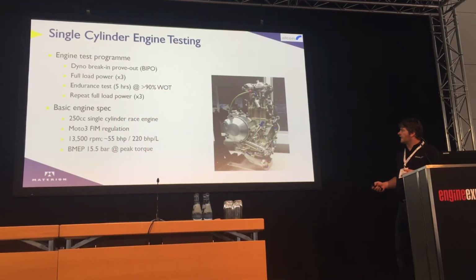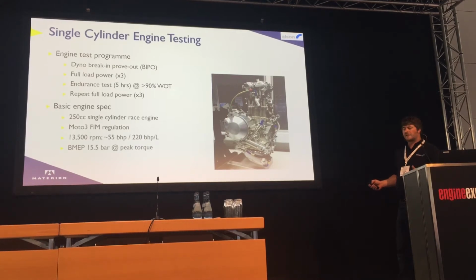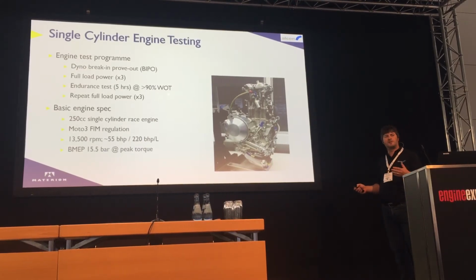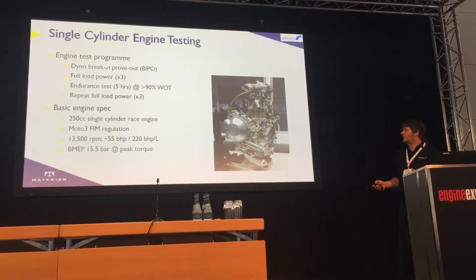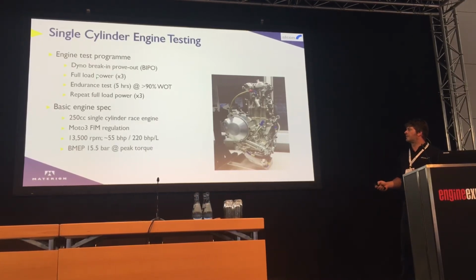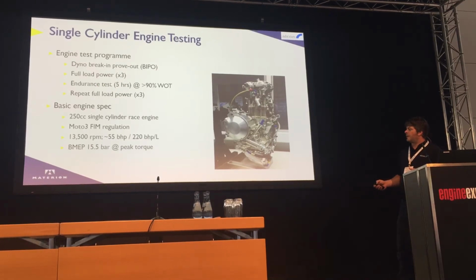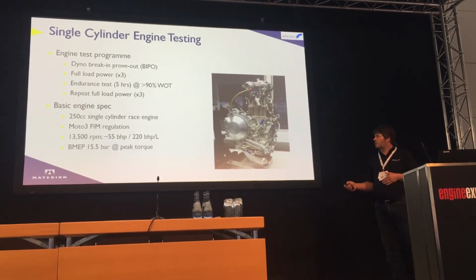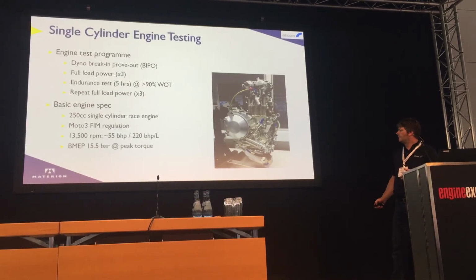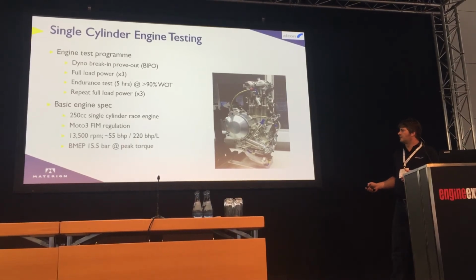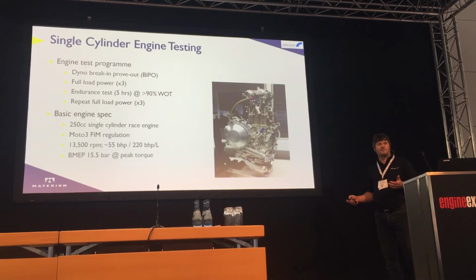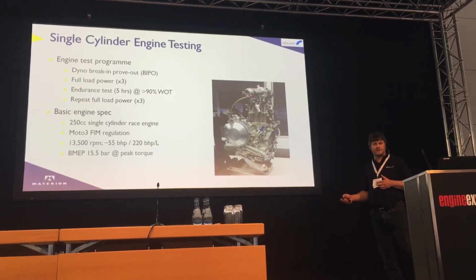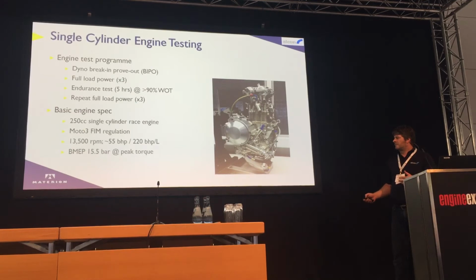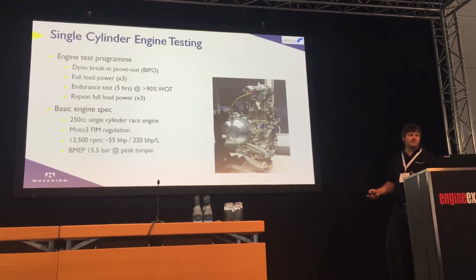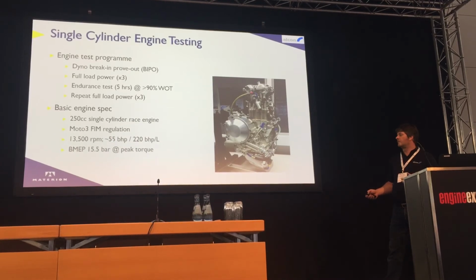The testing we did basically was a very simple set of tests, really just to prove the durability of the ring, to move on to multi-cylinder testing onto a customer program. So we did a basic break-in prove-out test, 3 power curves, and then we did an endurance test of 5 hours, greater than 90% wide open throttle, and we repeated that 3 times, stripping the engine at each stage to check the parts. We carried out on our own single-cylinder engine, so it's very much a race engine, but has a very high mean piston speed of about 24 meters per second, and it's naturally aspirated. BMEP is about 15.5 bar, cylinder pressure is about 107 bar.